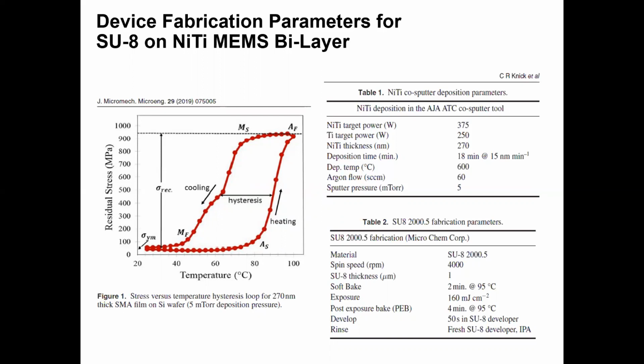Table 1 lists the NiTi co-sputter parameters, which included a 600-degree crystallization temperature, an 18-minute sputter, and yielded a high-quality SMA film of 270 nanometers thick, which was pretty close to the optimal value according to the contour map a couple slides back. Table 2 lists the SU8 parameters used to target a film thickness on the order of 1 micron, where a 4,000 RPM spin speed resulted in 1 micron of SU8, which was also intentionally close to the optimal value of 824 nanometers based on the contour maps I had shown.